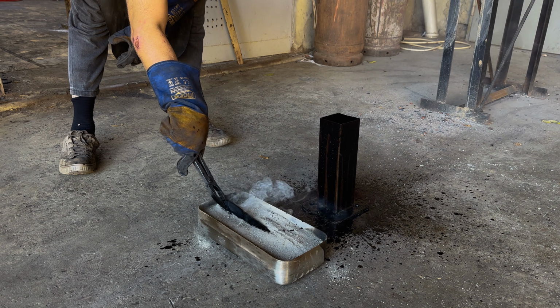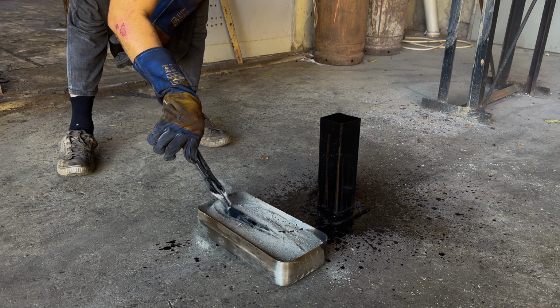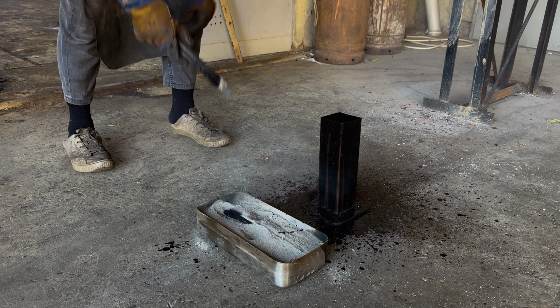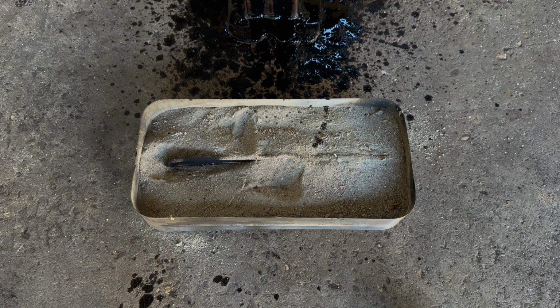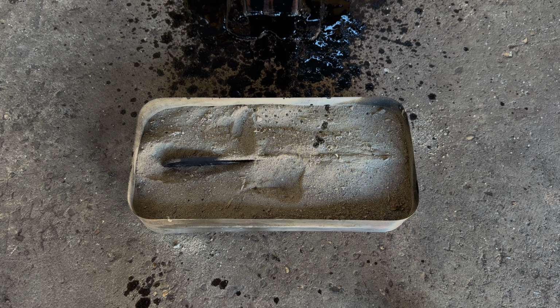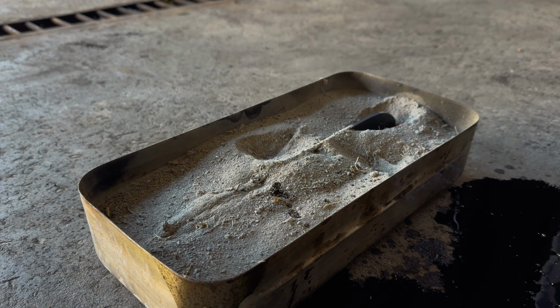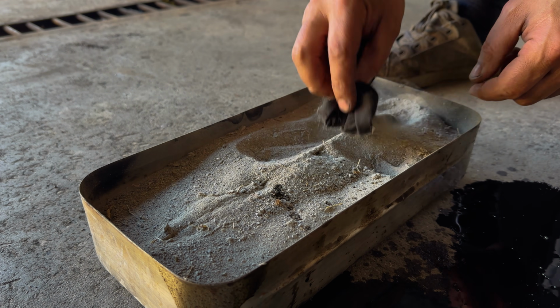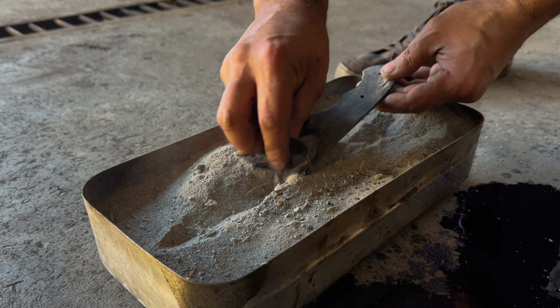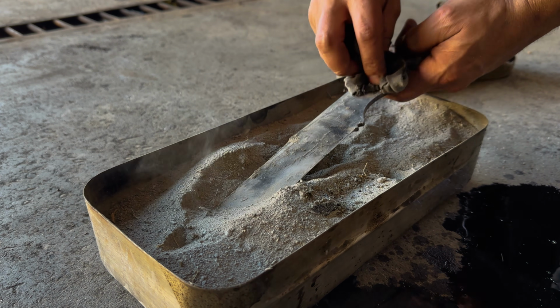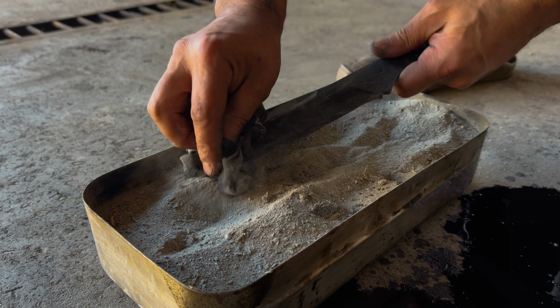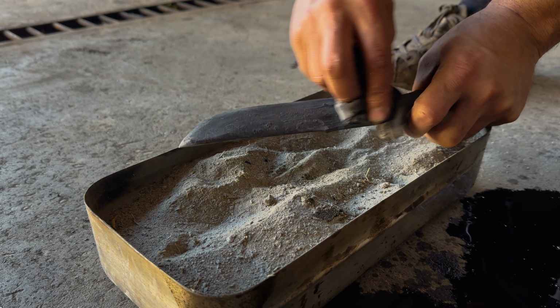Straight into the box of ash for a controlled, slower cooling process. We don't want any thermal shock cracking our blade after all this hard work. Digging our blade out of the ash pile like a buried treasure. Give it a rough scrub with a rag to clear off the baked-on crust so we can inspect the steel for any warping.